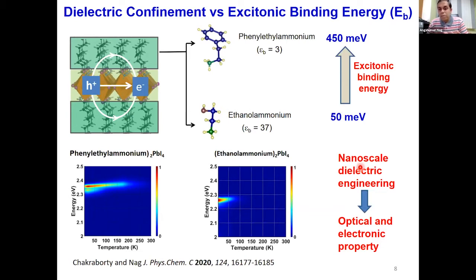And this is an example of interesting nanoscale dielectric engineering. For example, if you increase the thickness of this inorganic layer to something like 4-5 monolayers or 2-3 nanometers thick, then you will not see this kind of dielectric confinement effect. So it's a very much nanoscale, size dependent phenomenon, and it is not seen in a bulk crystal. And we have got these numbers of excitonic binding energy, etc., from low temperature photoluminescence data. And if you're interested in more details, you can look at the paper here.